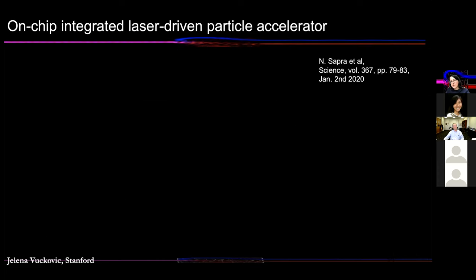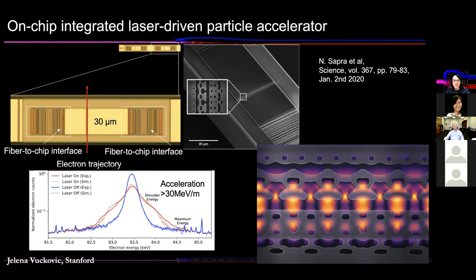So here is now the experiment, right? So you have the fabricated structures, and here, when you have no laser on at the input, you turn on your electron beam, and your electron beam exits this structure with the same energy that it had at the input, 83.4 kilo electron volts. When you turn the laser on, you accelerate electrons, and you accelerate them by about a kilo electron volt in 30 micrometers. So if you calculate gradient, it's 1 kilo electron volt per 30 micrometers, so that's 30 mega electron volts per meter.